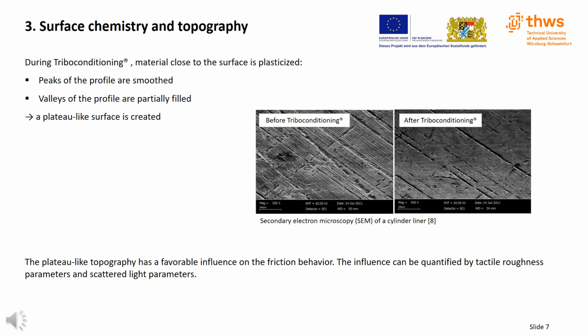The surface topography is significantly changed as a result of triboconditioning. This is because material close to the surface is plasticized and made flowable. The peaks of the profile are smoothed and the valleys are partially filled. This results in a plateau-like surface. The figure shows the surfaces of a cylinder liner by means of secondary electron microscopy. The left figure shows the surface before triboconditioning, the right figure after triboconditioning. It can be clearly seen that most of the finer grooves are eliminated due to triboconditioning. However, larger grooves remain. Such a topography with plateau character influences the friction behavior favorably.